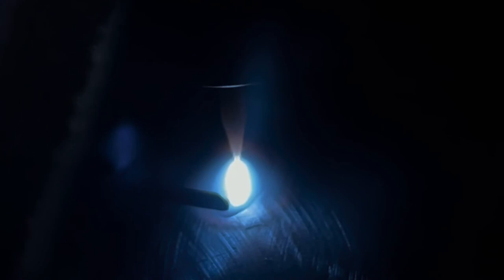This arc gap is a lot bigger probably than you'd want to run. I'm simply welding this while looking through my iPhone in a weld lens, so it's pretty difficult to see. But you can definitely see the arc cone itself is pretty narrow. When you weld on AC, it's super wide. Yeah, and you can see even the molten puddle is kind of shaped like a bean or something. It's not a distinct round leading edge of that puddle, which is a good indication the arc gap is too long. Anytime you start seeing that, either the amperage is too high or the arc gap itself is too long. Because if you tighten that up, it'll clean that leading edge up.